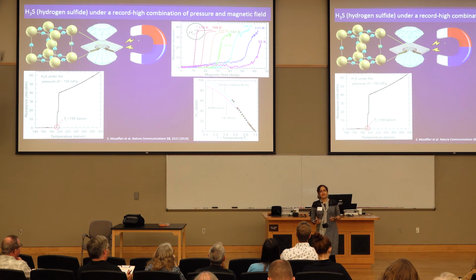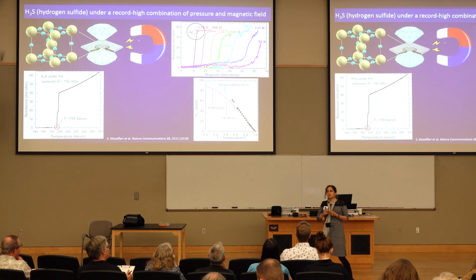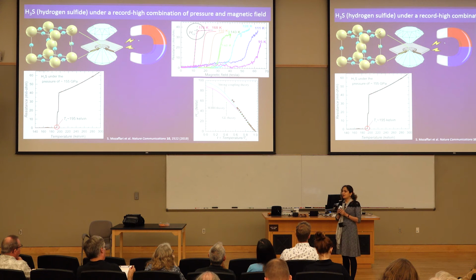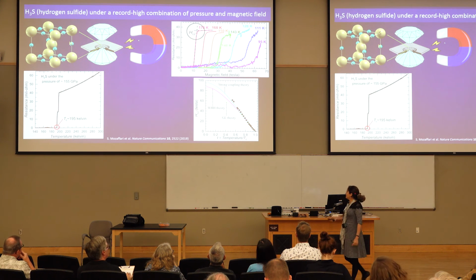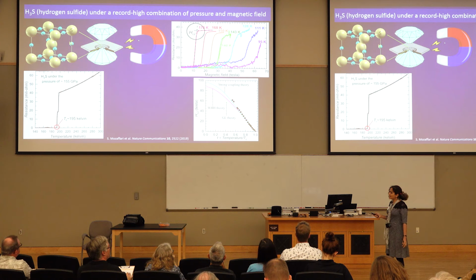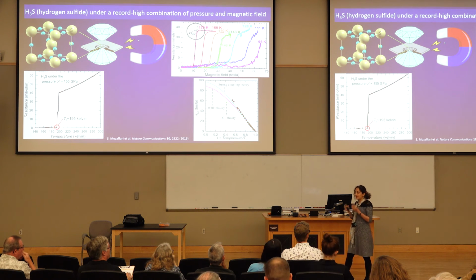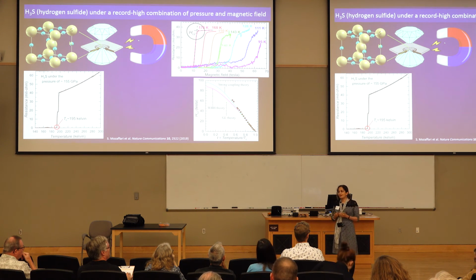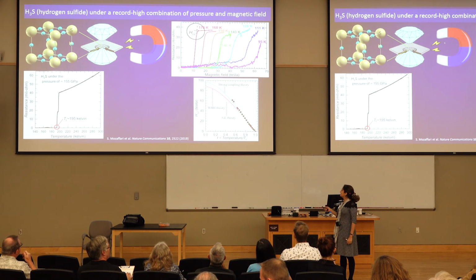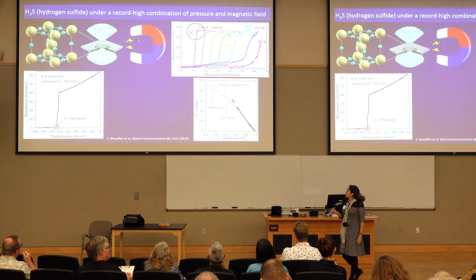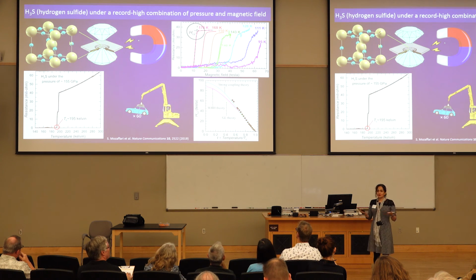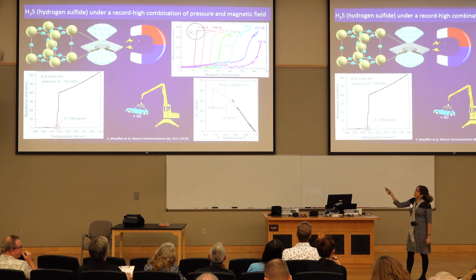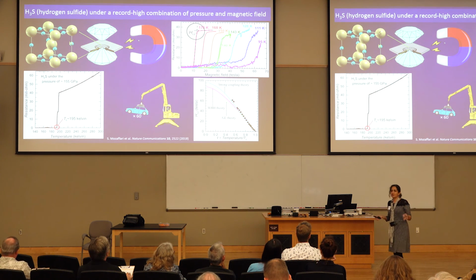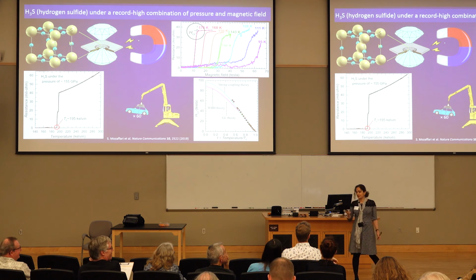This theory explains that in a superconducting state, electrons form pairs, and they are very strongly bonded to each other. In fact, in H3S, they are so strongly bonded that to break the superconductivity, we needed a magnet which was stronger than the 60 Tesla magnet available. This 60 Tesla magnet is so strong that it can lift up to 60 cars. So, our result, which is a record high combination of applied pressure and magnetic field, can provide feedback to theory.